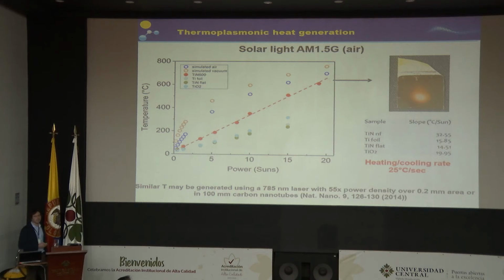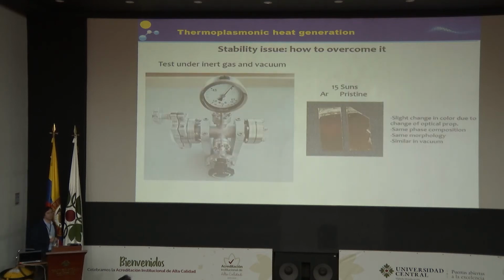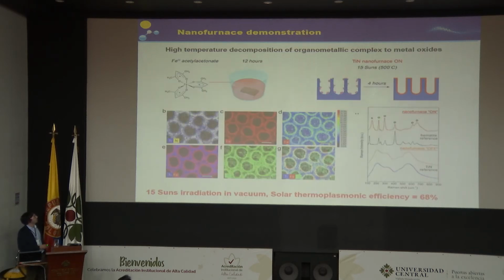In air, the titanium nitride is not stable, but if you use argon or vacuum, our material is stable. And I just want to go to the application. What we did was to shine light at 15 suns onto our materials, which were previously immersed in a solution of iron acetylacetonate. After illumination of 4 hours in vacuum, we see the disordered deposit transforming into a conformal coating.